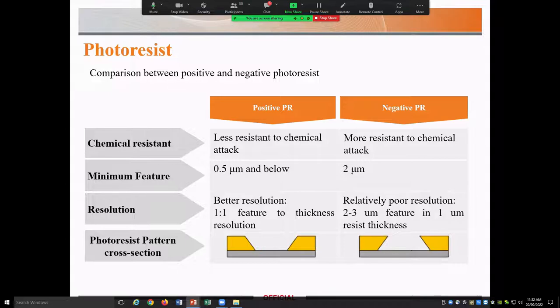Also, the sidewall profile we can get from these two photoresists is different. The positive resist usually gives us a positive sidewall profile, and negative resist gives us a negative sidewall profile. It is quite important for some processes. For example, for the liftoff process, we prefer to have a negative sidewall profile. Of course, this can be modified by different factors like thickness of photoresist, type of photoresist, or even the exposure dose.